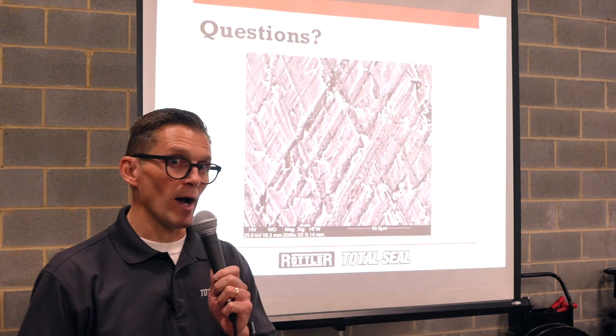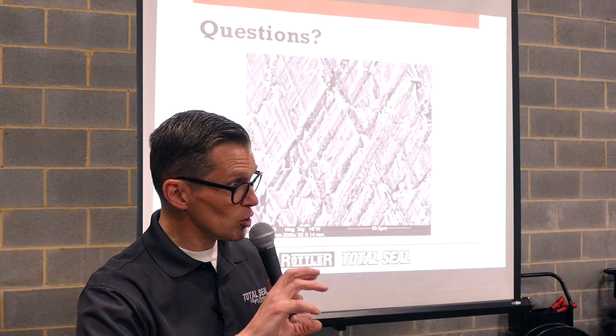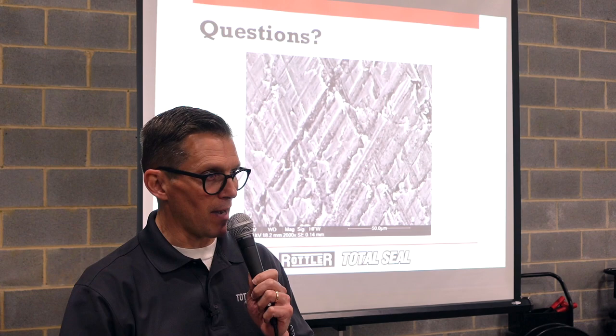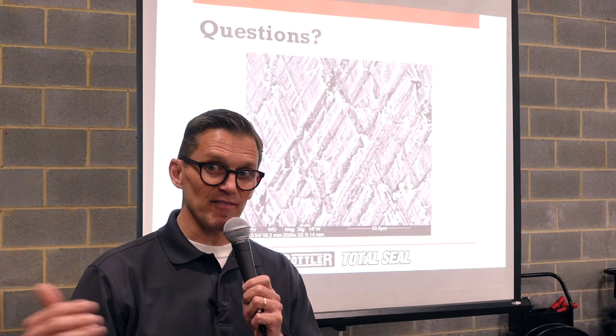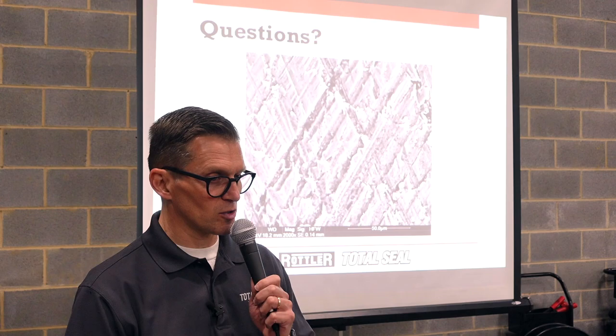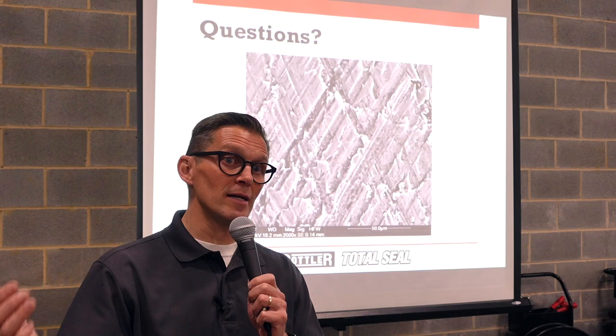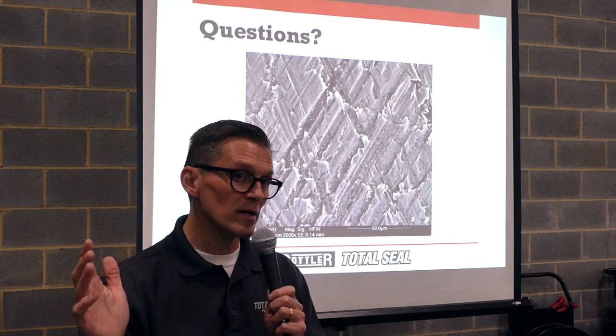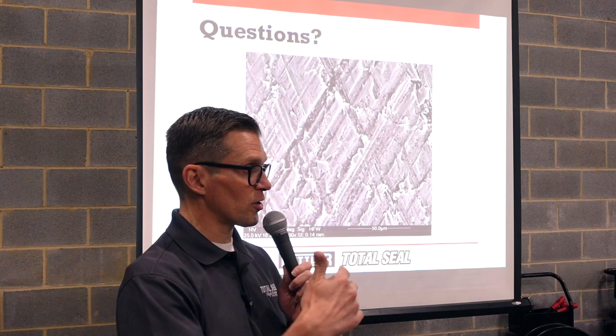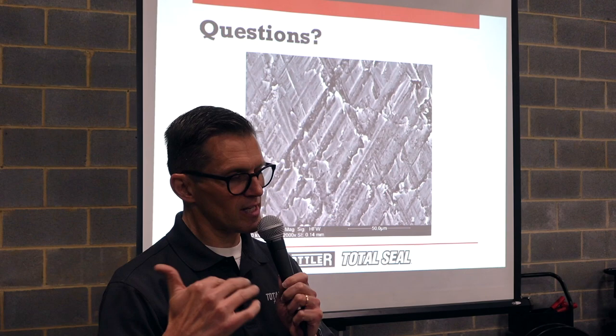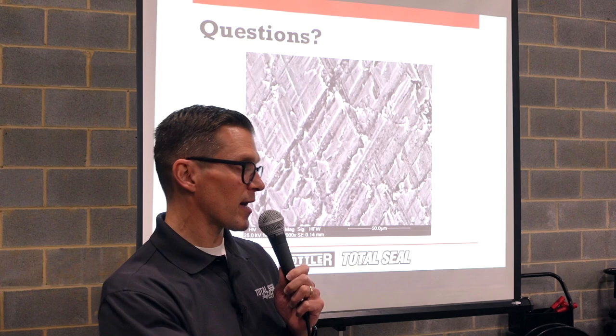I'm going to tell you right now, the current API SP, which is the newest one, is the best oil that I've seen in my lifetime. The reason it's better is because they've lowered the detergent level. Calcium and sodium, which are traditionally detergents in motor oil, can cause low speed pre-ignition in direct injection engines. Because the majority of internal combustion engines being built by the OEMs today are direct injected, they had to come up with a new additive package and a test that screened for low-speed pre-ignition. So it eliminated all the sodium in the oil. There aren't shelf oils now that have sodium detergent in them.